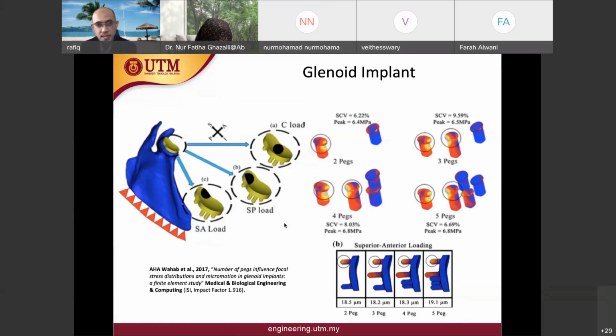So we compare this glenoid implant between 2 pegs, 3 pegs, 4 pegs, and 5 pegs. Again, the implant is this small. The glenoid implant is that small. And the whole idea is to prevent the rocking horse phenomenon, because after you insert the glenoid component there is a risk of the glenoid implant loosening. So the pegs are there to prevent any major micromotion. And then we look at the stress and of course the displacement between the 2 pegs, 3 pegs, 4 pegs, and 5 pegs.